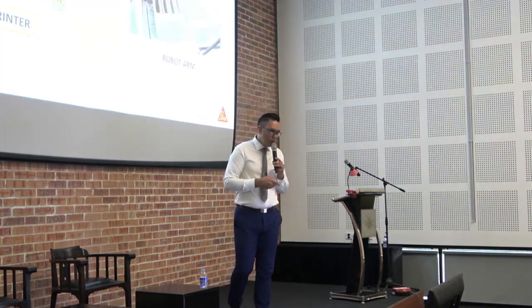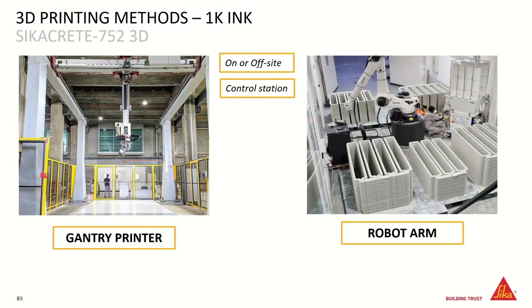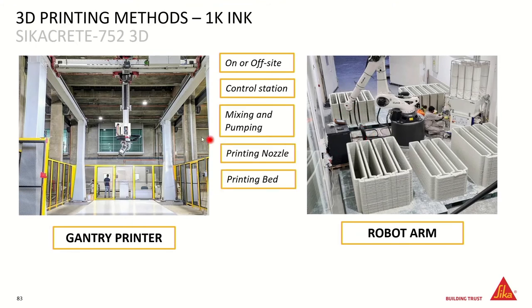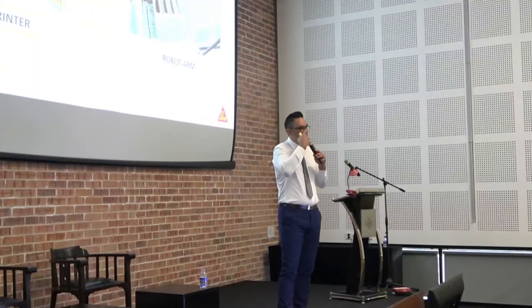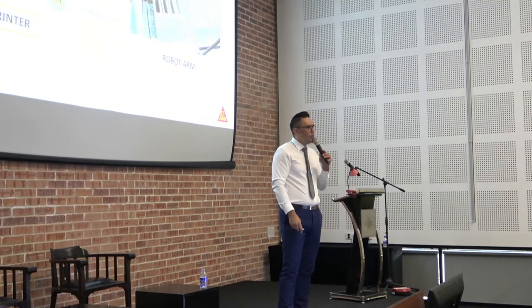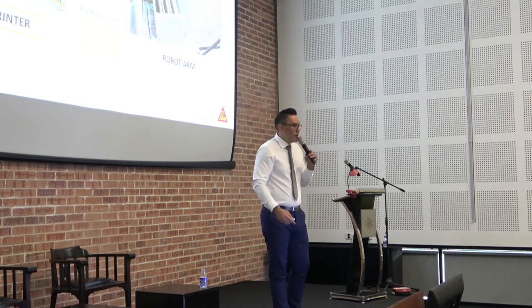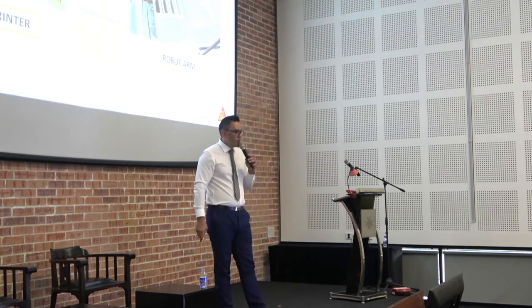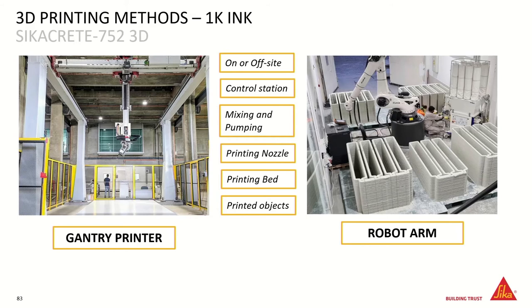So what do we need? For a one-component ink, you need either this robot on the right-hand side here or a large gantry with XYZ axis capability. Now, the investment will depend on your business plan or the outcome will depend on the business plan long term, because they can be quite expensive or they can be quite reasonable, depending on what you want to print. So that's a very large scale printer on the left that'll, I think, print up to 7 meters high, 9 meters long. So it's quite large. And a robot arm, you can see, you can just multiply around. If you were going to extrude those or cast those in concrete, would probably take longer to set the formwork up than it does to print.